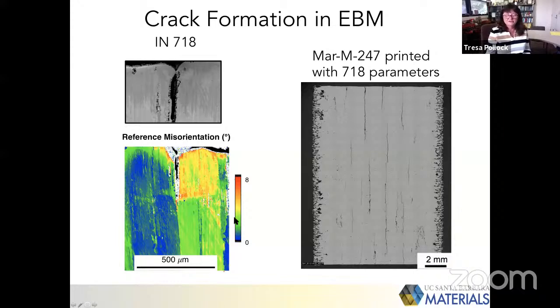And so just to put in perspective that 10 degree misorientation, here is a couple of different materials. Here's the 718 that we've been working on. When you get something of the order of 8 to 10 degrees, you might expect a crack to start to develop while printing these materials. Here's another alloy, Mar-M 247, and you can see that there are cracks that have been developing throughout the build.